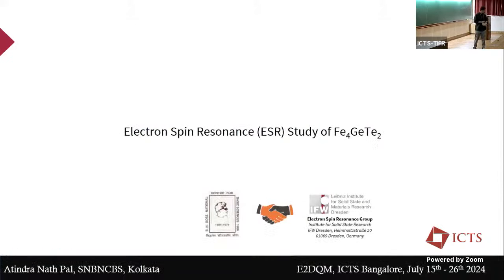So in the last 10 minutes or so, I will discuss the electron spin resonance experiment, because from the transport data we observe a Fermi surface reconstruction, and we have two kinds of transition in the Hall data. We also observe them in the resistivity data as well as in the magnetoresistance data. Now to understand or measure the anisotropy quantitatively, the ESR experiment can give you a lot of details.